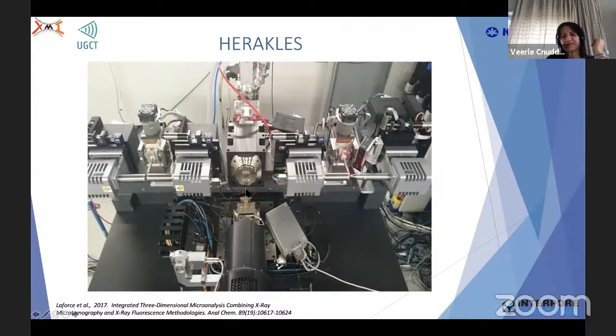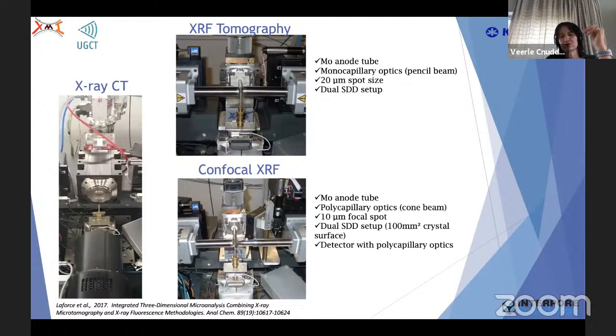So the sample is first scanned, and then with software we say, okay, we want to have a point analysis at this spot, and it automatically goes to one of the end stations. So we have CT and two end stations: one is specifically for X-ray fluorescence tomography with a focal spot of 20 micron, and the other is for confocal XRF where the focal spot is 10 micron. So higher resolution in this case, higher sensitivity, but the other one gives you the ability to do a kind of 2D chemical mapping.